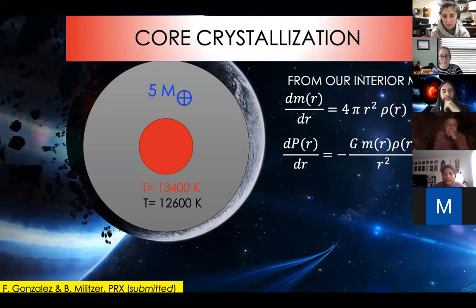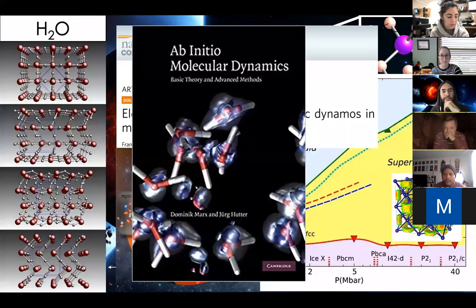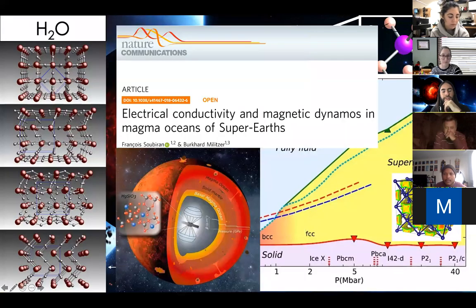Yeah, you're totally right, and that's basically one of the studies that I showed you in the beginning. This one here was done in our group by Francois Soubiran and Burkhard Militzer, where we can basically calculate the electrical conductivity. So it's not superconductivity, just normal electrical conductivity, and calculate what's called the Reynolds magnetic number in order to have an estimate of how much magnetic field you can generate in a convective layer where you have this conductive material. So yeah, that is a possibility, and that's one way to address it, which is really interesting.